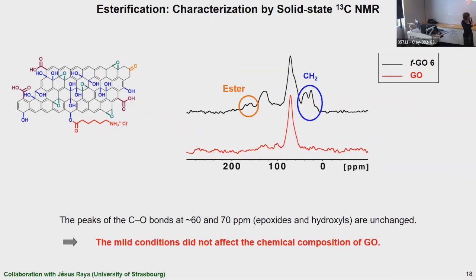So in red, you can see the spectrum of the starting graphene oxide. After the reaction, we were delighted to see peaks here corresponding to the CH2 of the linker, and most importantly, to see this peak here, close to 170 ppm, confirming the presence of the ester bond. And also, what we can notice is that the peaks of the epoxides and hydroxyls were unchanged after the reaction, showing that here the conditions were mild and did not affect the chemical composition of graphene oxide.